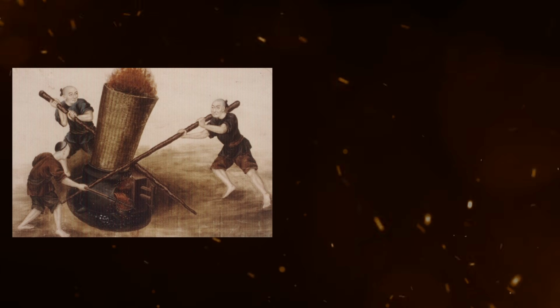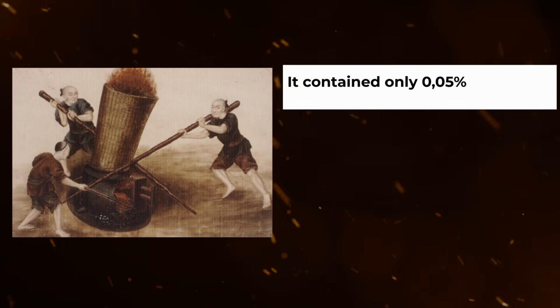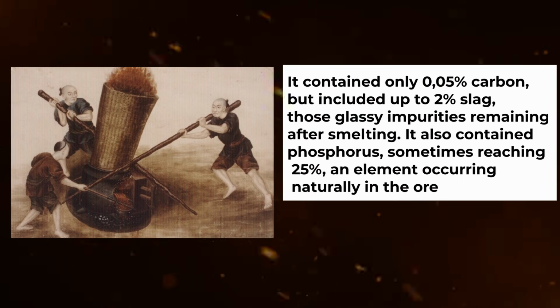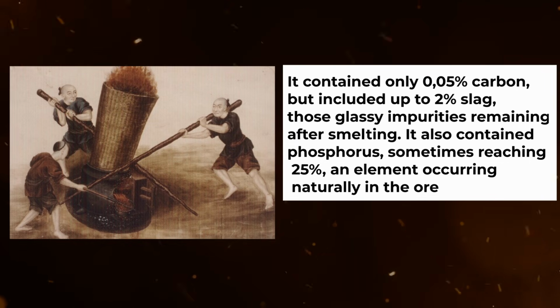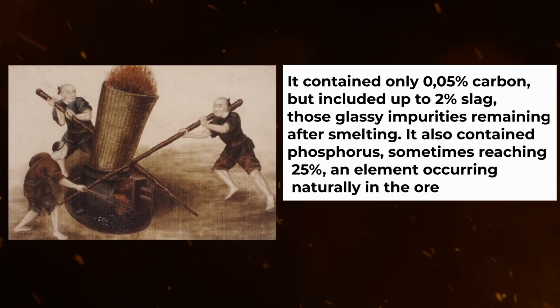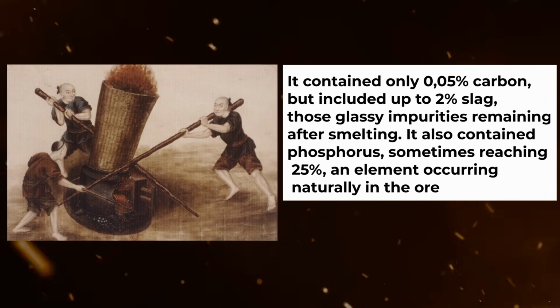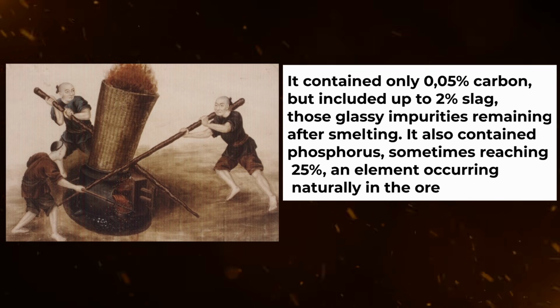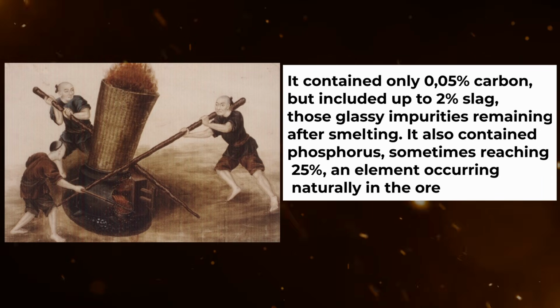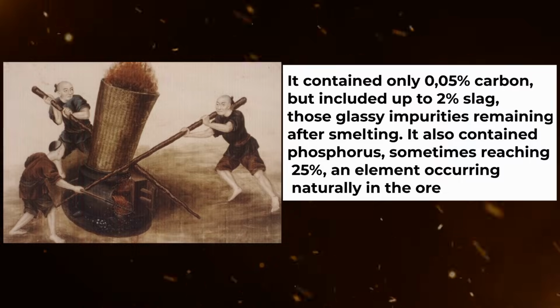Ancient Chinese wrought iron told a completely different story. It contained only 0.05% carbon, but included up to 2% slag, those glassy impurities remaining after smelting. It also contained phosphorus, sometimes reaching 0.25%, an element occurring naturally in the ore.